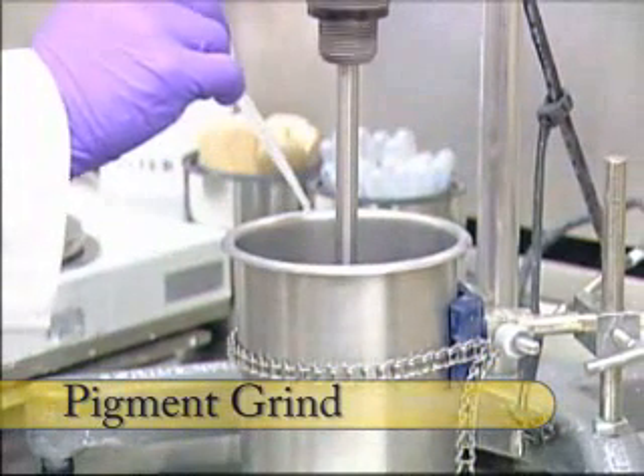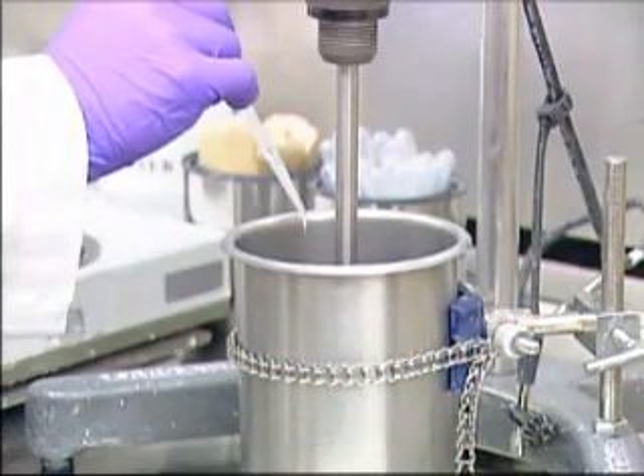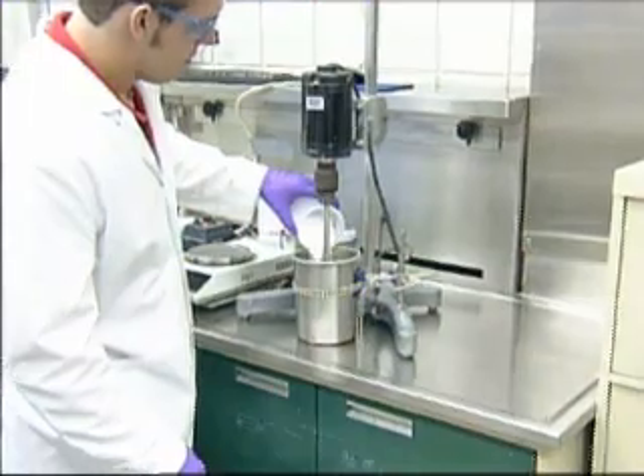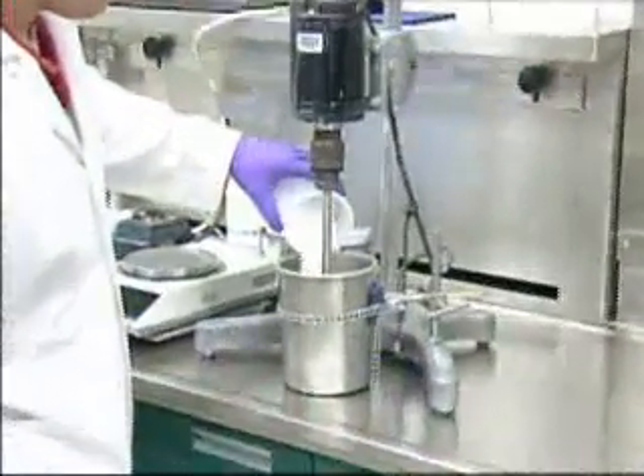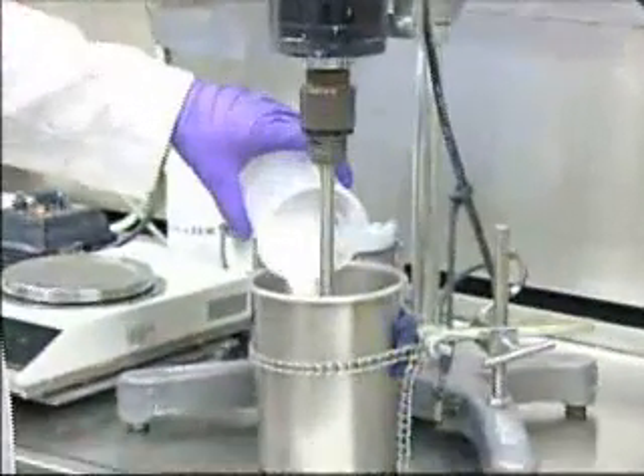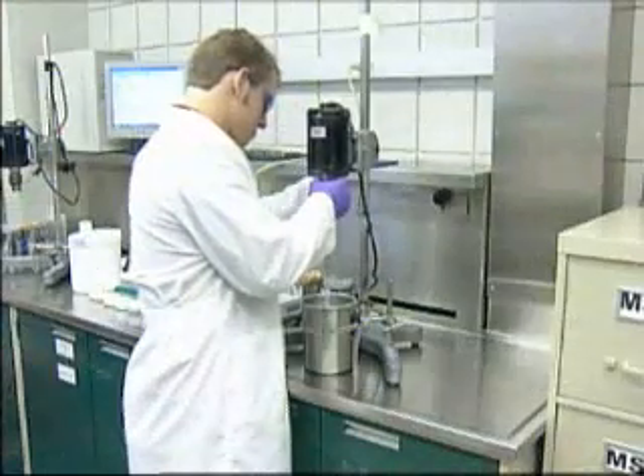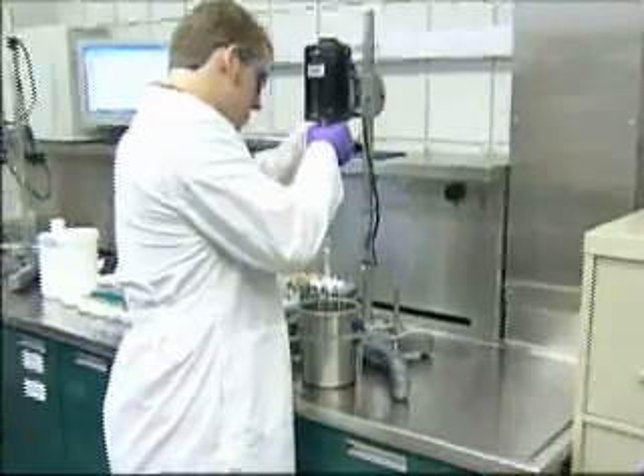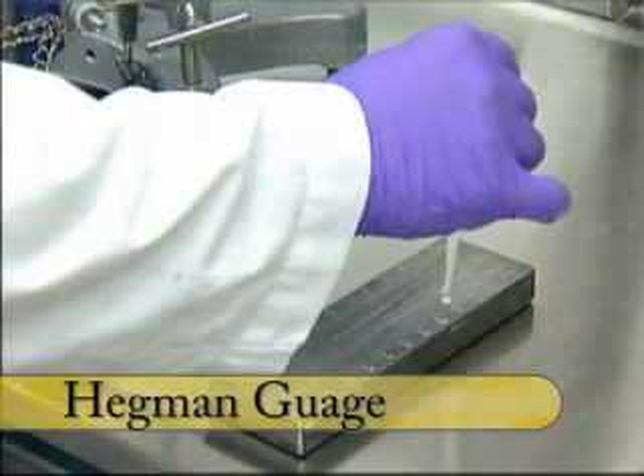The first step in making waterborne architectural coatings is the formation of a pigment grind. Here, mechanical agitation is used to disperse pigments into water using dispersing agents. In the next step, the latex and additives are blended with the pigment grind to complete the coating formulation.